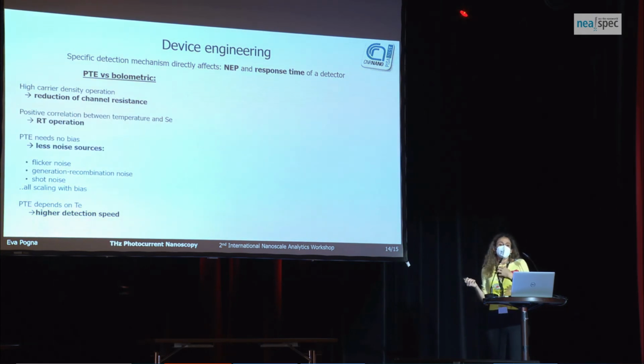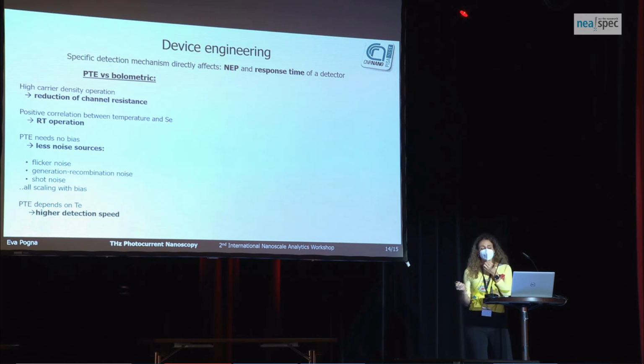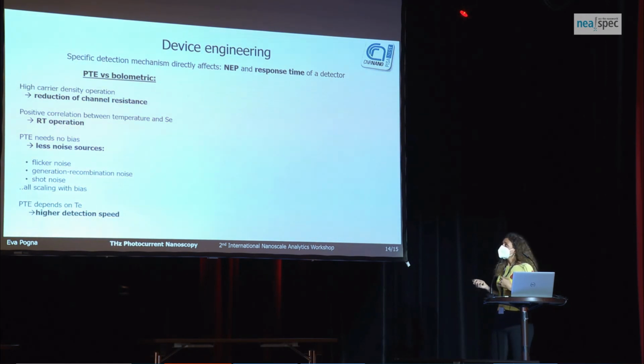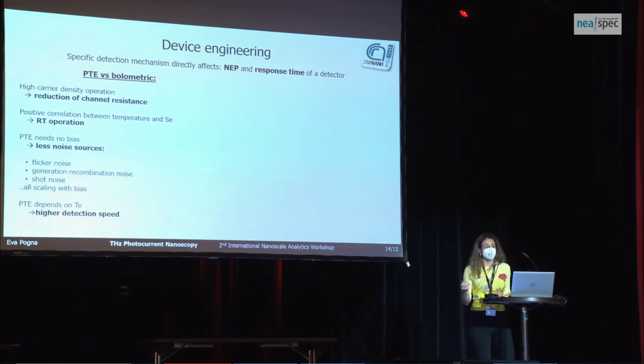So the photothermoelectric effect has some advantages over the bolometric mechanism for detection, because it needs no bias. So we can get rid of a lot of sources of noise. And also because it's exploiting the positive correlation between the lattice temperature and the Seebeck coefficient, it can support room temperature detection. And because it relies on the electronic bath heating, it would support the detection at higher speed.